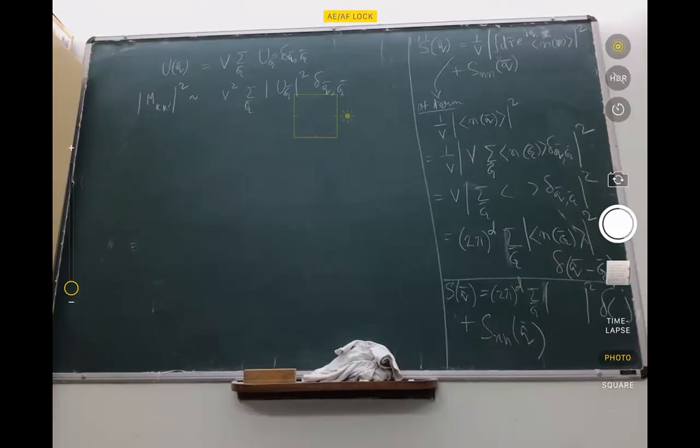But as I said, in a real crystal, that never happens because, apart from other defects, you are always at a finite temperature. So there will be some thermal motion of the atoms. But even otherwise, you could have quantum fluctuations, which would give you some diffuse nature and weight to these peaks in S(Q).